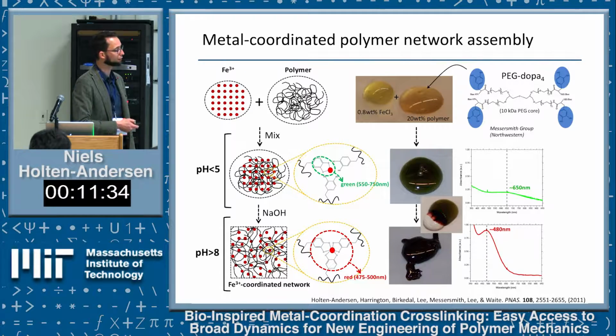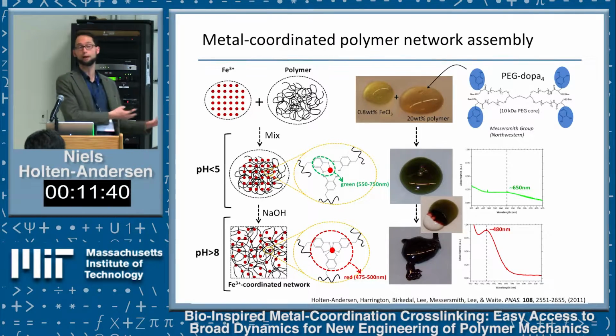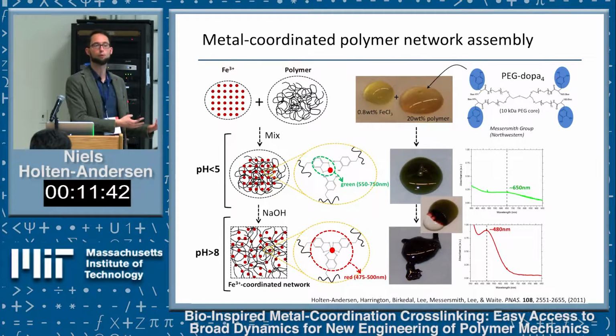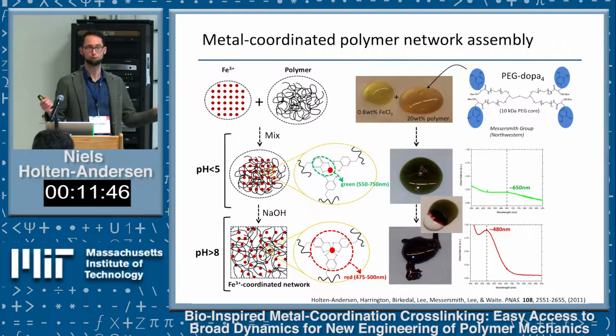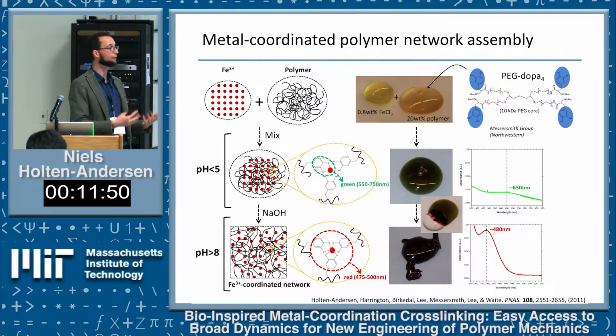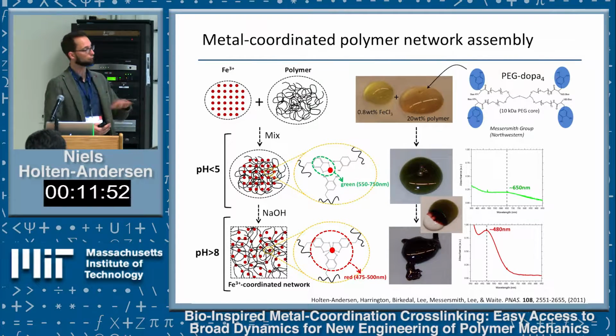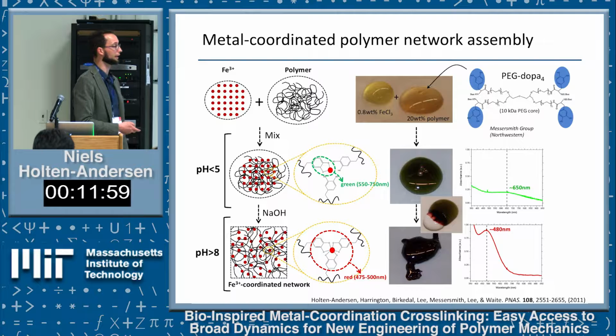All we then do is mix this around physically, and you get this silly putty-like viscoelastic hydrogel—a hydrogel with not a very high polymer weight percent and not a lot of metal ion. It's already a very tough hydrogel, purely because it's held together with these dynamic bonds. So it's a very simple crosslink chemistry to rapidly go across a fluid-solid transition with a simple chemical—that's definitely what the mussel is taking advantage of.